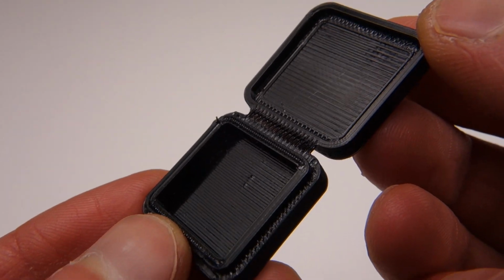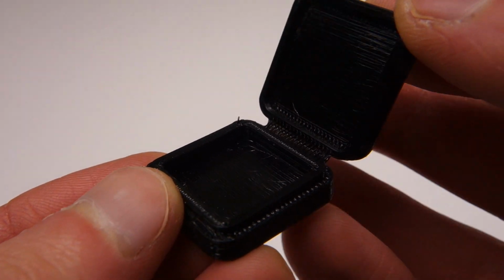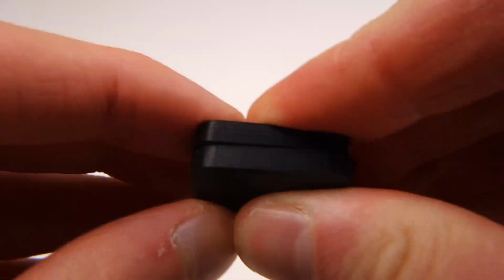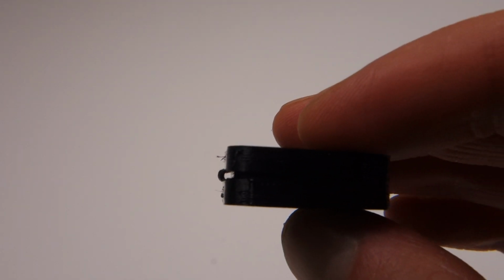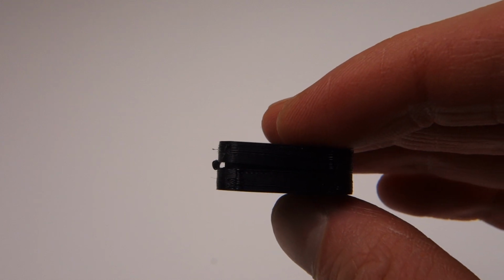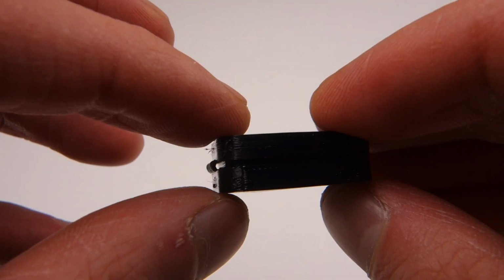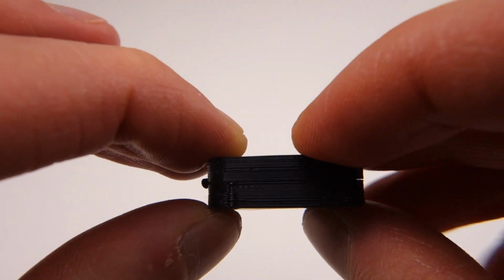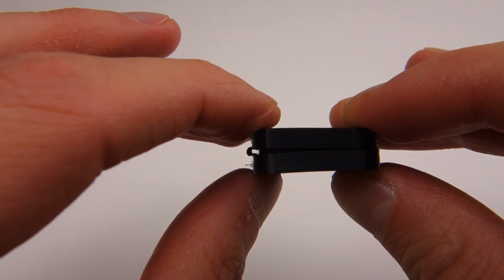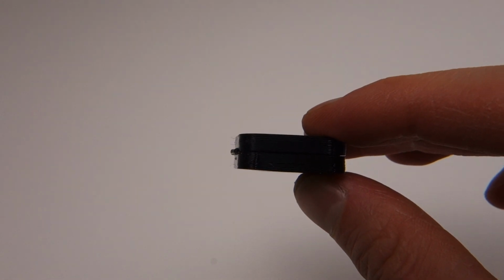So instead, we will use a flexible material, Cheetah. And as we can see, it works great. But if we zoom in, we can see that the hinge lifts up the case in the back. And this is because the hinge is flush to the separation line, leaving no room for the hinge to bend. So what we're going to do is lower the hinge slightly below the split line. And now the case fully closes.